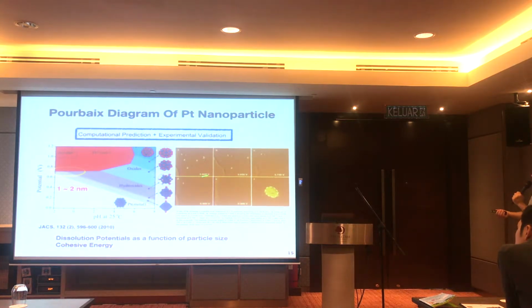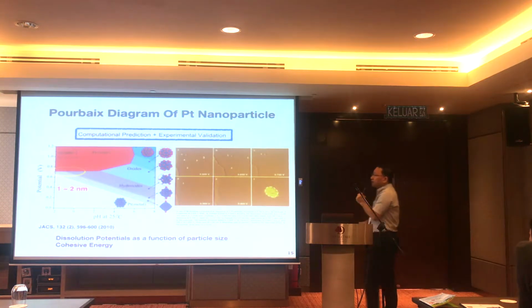Also, this result was validated by in situ STM in another group, not at MIT. The other group measured the dissolution potential as a function of particle size. They scattered platinum nanoparticles of different sizes on a gold support, and they held certain potentials, maybe 10 or 20 minutes, and then they figured out that certain particles were gone here. Number 4 and 5 are gone. They know exactly the size of 4 and 5. Number 5 nanoparticles dissolve at 0.6 volt. So they kept the record by hand. Then they compared with our result, and we found very good agreement between experimental validation and computational predictions.